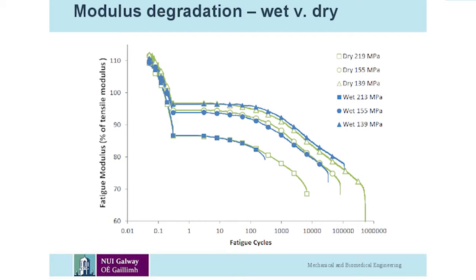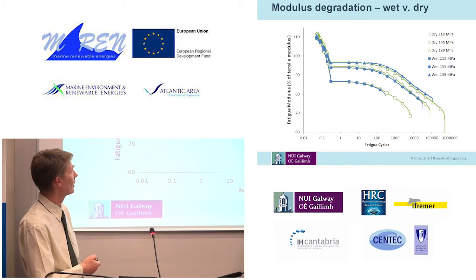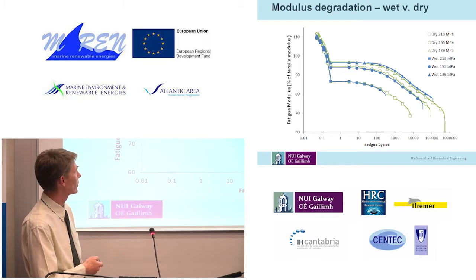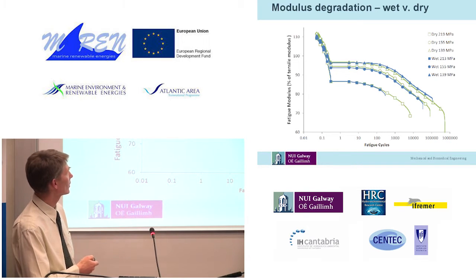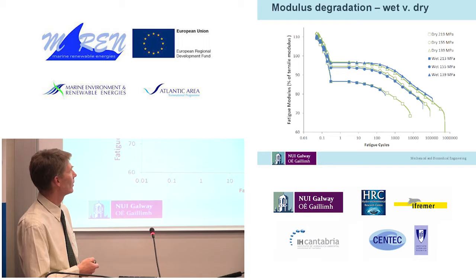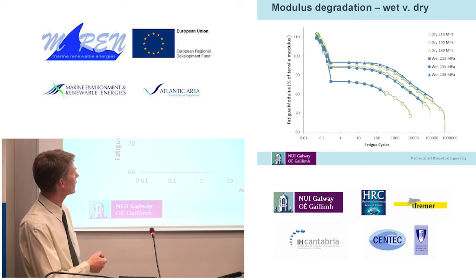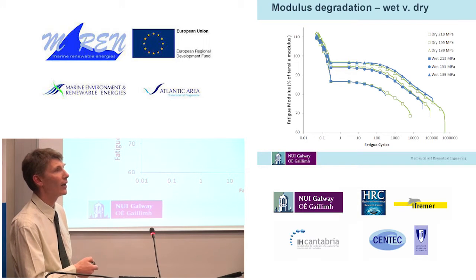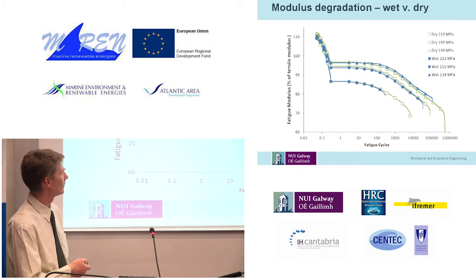I guess the interesting thing for me is that if I put the wet results on top of the dry results here, you can see that there's just about no difference in the response or in the evolution of the fatigue modulus between wet and dry samples. So I think the only thing that you can see here is that the wet material stops sooner, and that's because it fails earlier. But other than that, it's very, very similar.